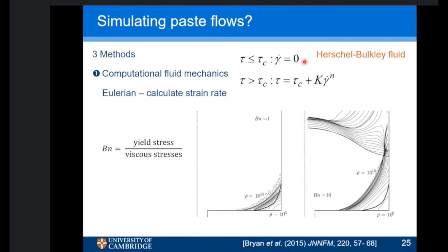Okay, so it's got a bifurcation: below some criterion for yield stress or critical stress, your strain rate is 0. Above that, and this is the deviatoric shear stress, you have a relationship which gives you the relationship between the stress and the local strain rate. And usually this is done in a Eulerian way, and you capture the strain rate.